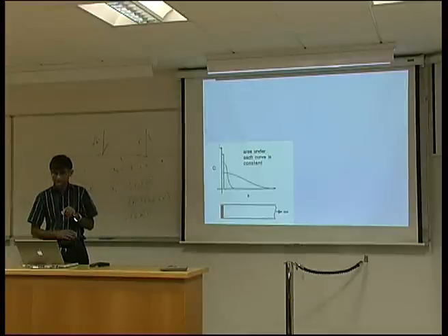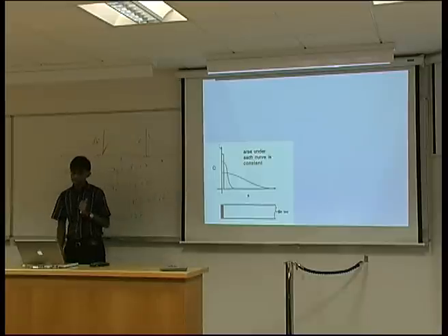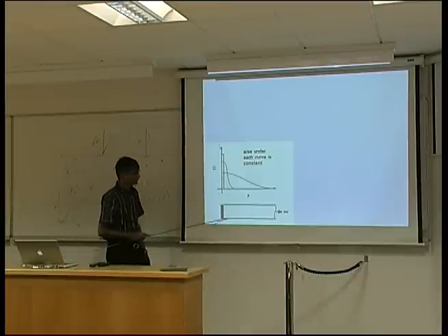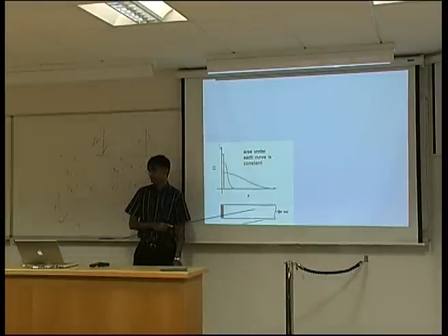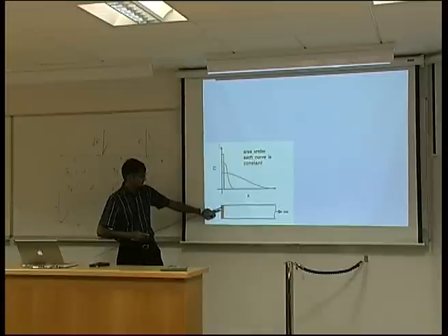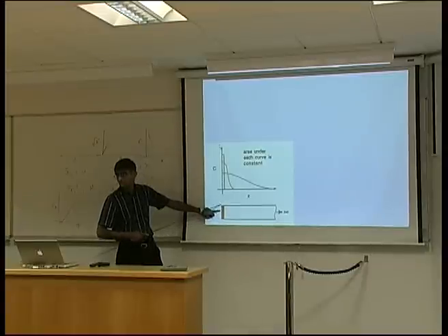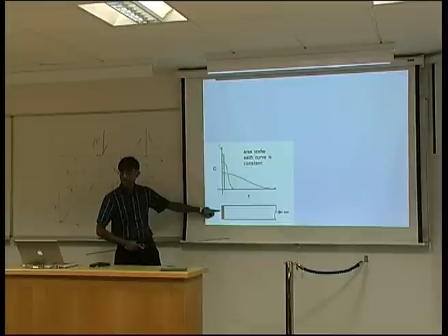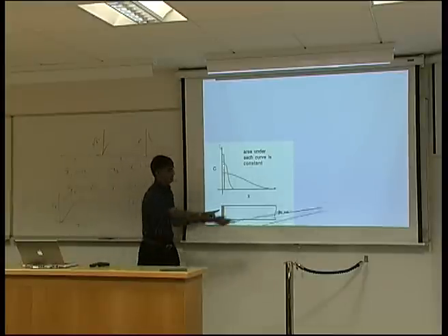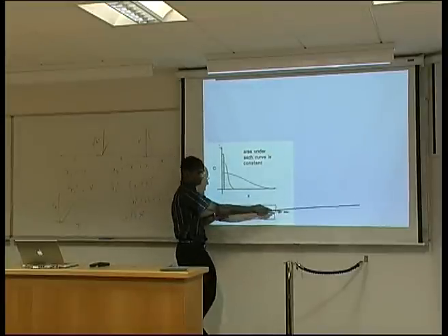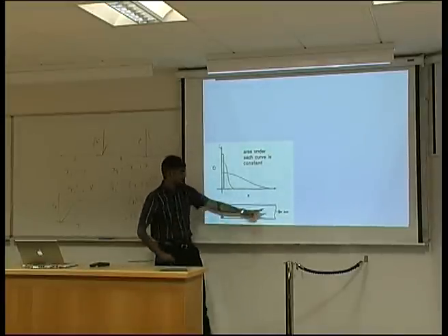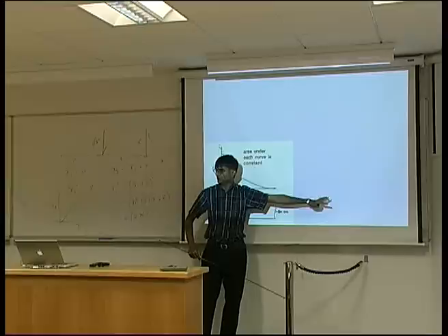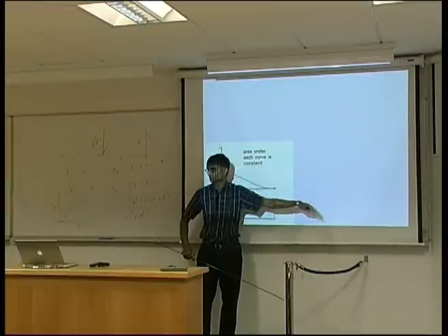Okay, so let's derive the first useful solution. So we're looking at what we call a semi-infinite bar. So we have a bar, we've plated some material on top of it, some solute. Let's say this is silicon here, and we've put a layer of phosphorus on top, and that this is long enough to be treated as semi-infinite. In other words, the concentration far away is not going to change.